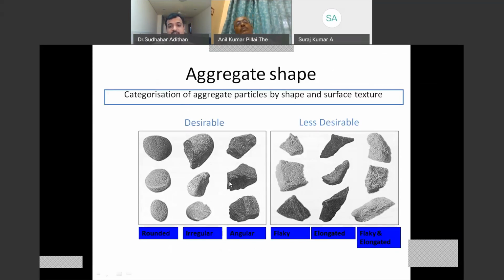So the desirable shapes are mostly rounded, irregular, and angular. Rounded and irregular are very difficult to manufacture. Angular is easily manufacturable through the modern VSI systems of MSAND manufacturing. What should not be there is flaky or elongated aggregates, as you would appreciate that this will create a lot of interparticle friction and therefore will not allow the concrete to flow. So if you have to achieve workability, you will have to achieve it either by increased fine aggregate content, which means you will have to add more cement and you will kill economy, or through increased water cement ratio, which will bring down the strength of the concrete system, or through increased usage of admixtures, which will again not make your cost effectiveness so viable.